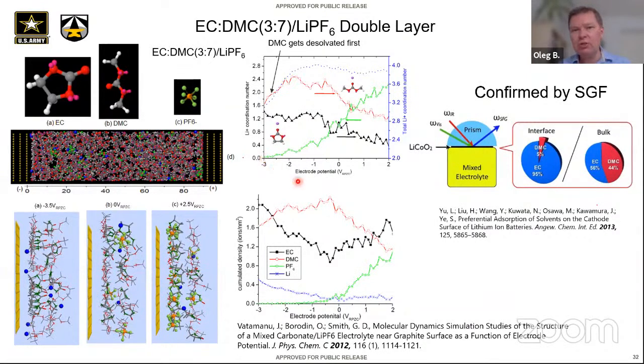bulk simulations, right? So we take the bulk structure and say, well, that's aggregated. Once we polarize it very negatively, it's going to be less aggregated. So that needs to be taken into account when we are using bulk structure to say that's the aggregation number. It will be less on the negative electrode than in the majority of the electrolyte. And the other important ramification is that DMC gets desolvated first, right? So lithium comes in, EC stays, DMC gets desolvated first.